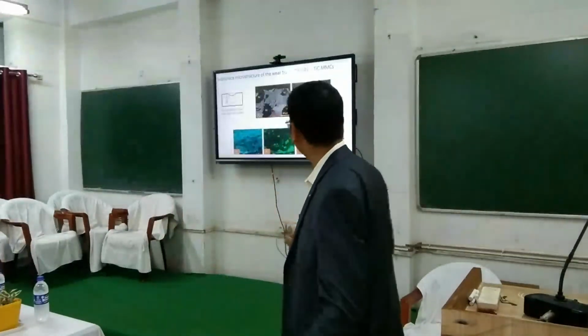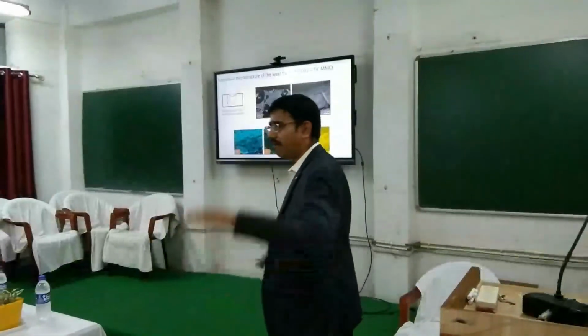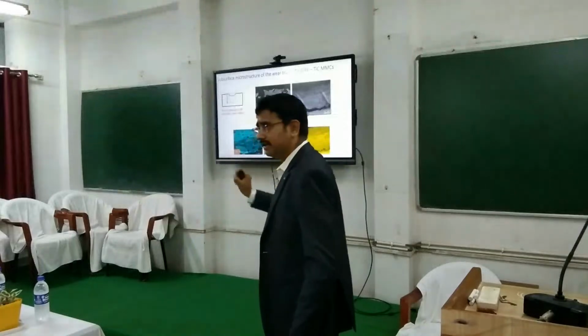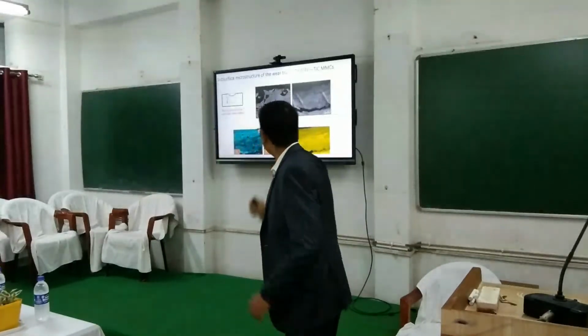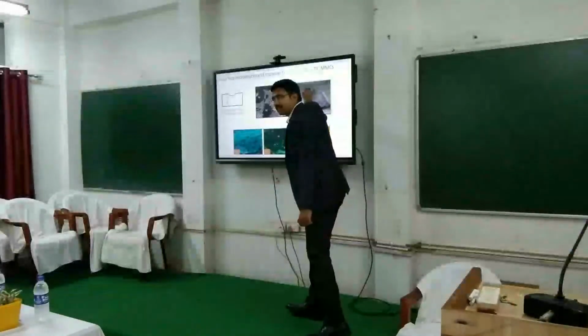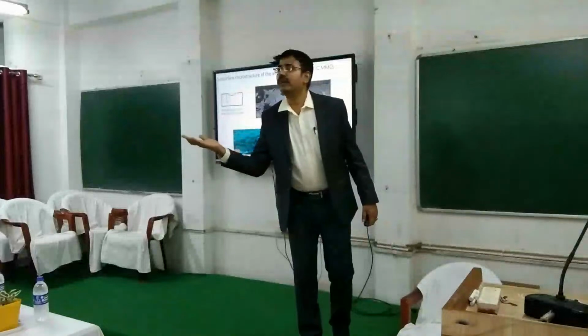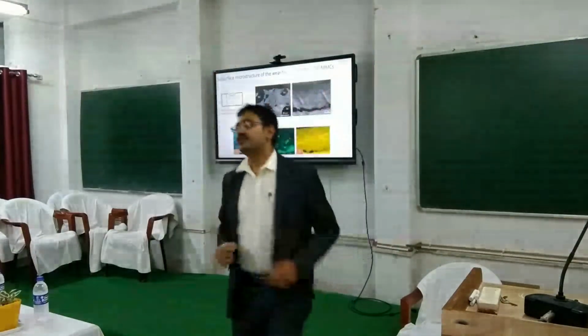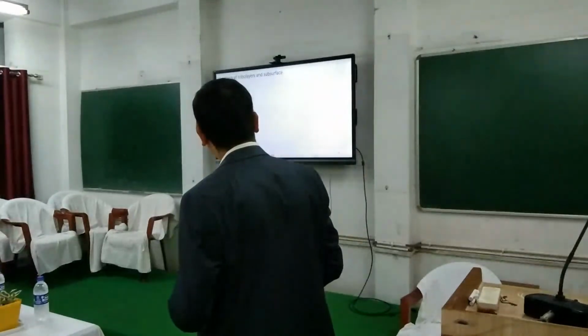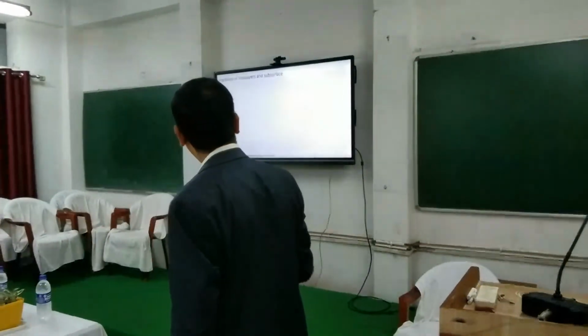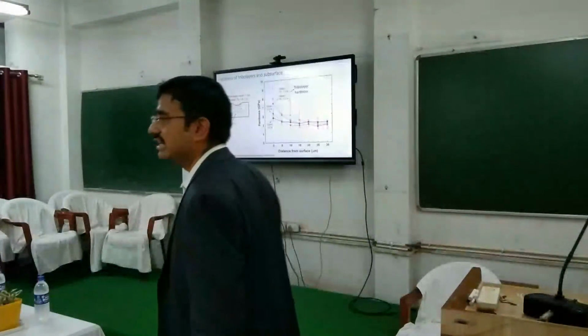So we also looked at the chemical composition of the tribolayers. You see that apart from having this lubricating phenomenon, the carbon particles also got fragmented and got embedded inside the tribolayer. So you see these small particles inside this tribolayer, they are small carbon particles which are present. They give the load bearing support for the load which you are providing. So this is the deformed microstructure, and lastly we also measured the hardness of this tribolayer.